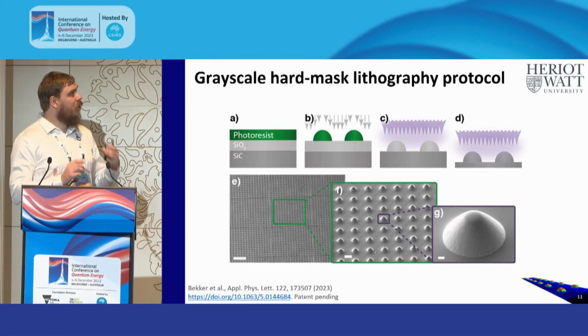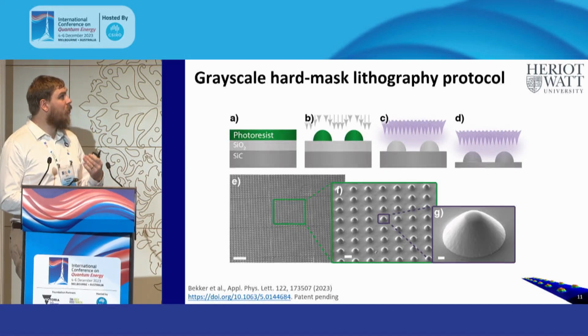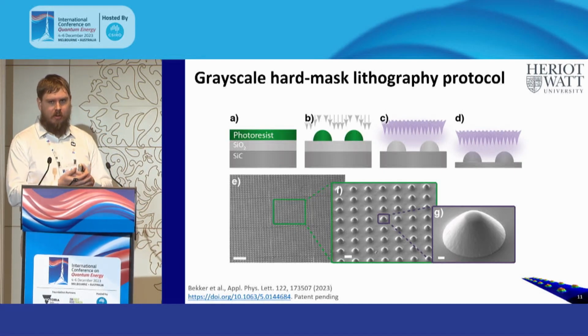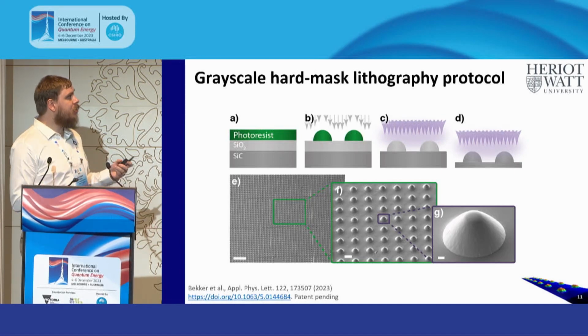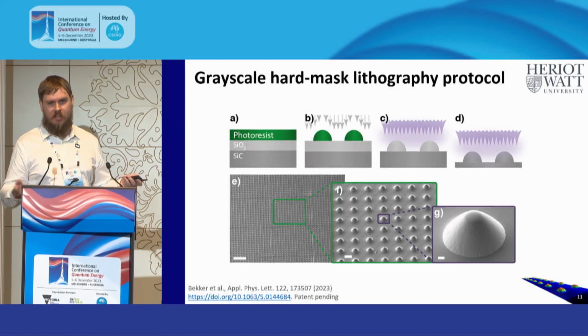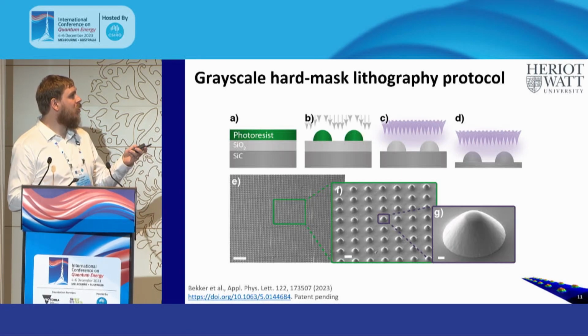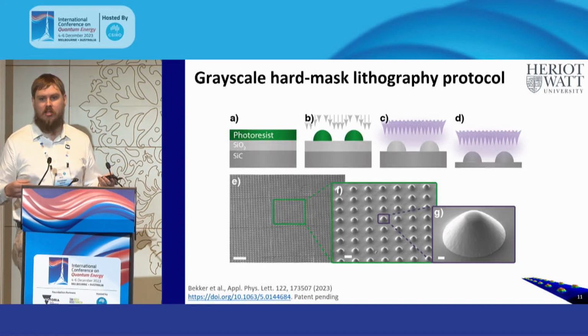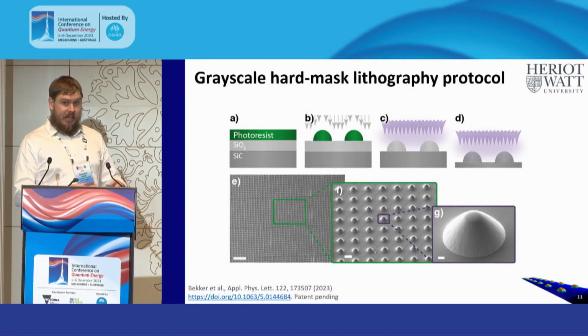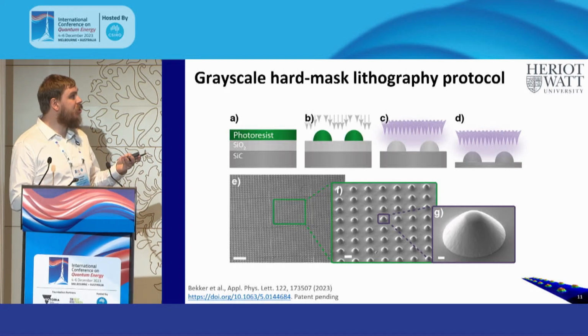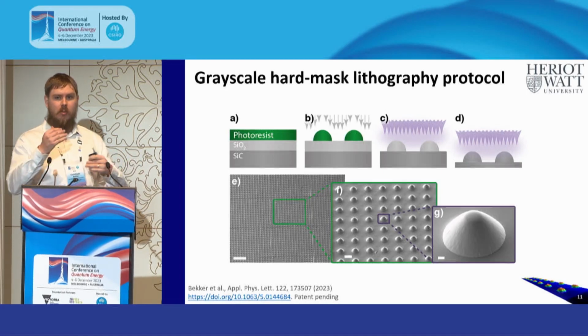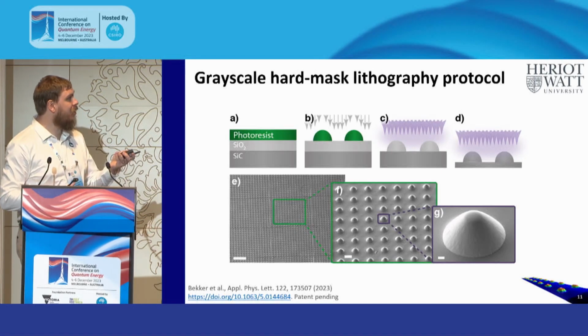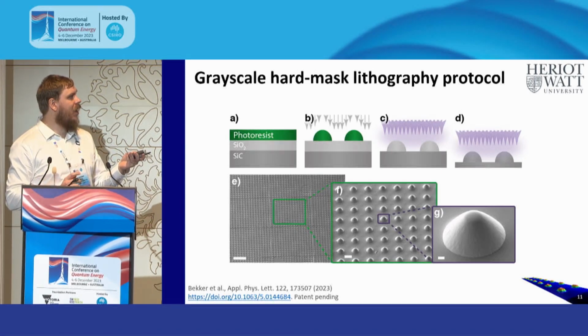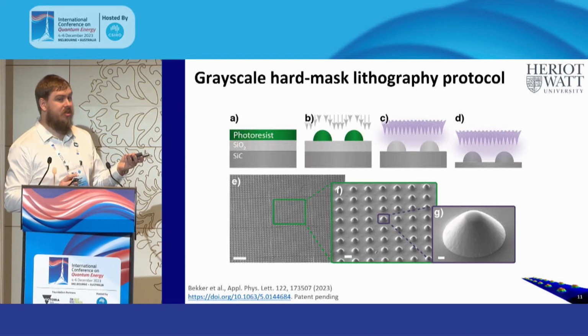So what we wanted to do was add what we call a grayscale hard mask to our lithography protocol. Normally when you do photolithography, if you want to make a device like I was mentioning before, we have our resist and we go straight from this and imprint our shape into our substrate. By adding, in this case, a separate material, we actually decouple. We create two etch steps. So we imprint our resist into our hard mask, in this case glass, and then imprint the glass into silicon carbide.